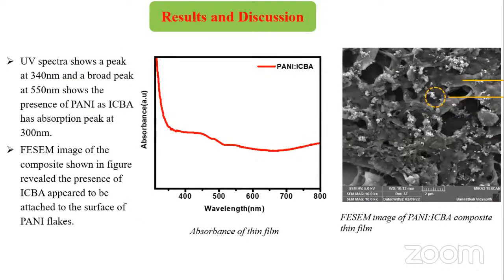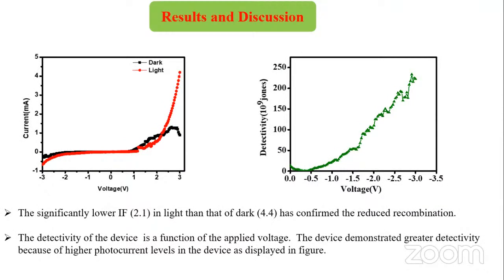We can clearly see the absorption spectra for the active layer, as the peaks for PANI and ICBA are clearly visible at 340 nanometer and 550 nanometer. As you can clearly see, the low band gap polymer increases the absorption area so that the number of photons absorbed increased for this particular optoelectronic device. And next is the FESEM image, where we can clearly see the presence of PANI flakes and the ICBA, which is the fullerene derivative.